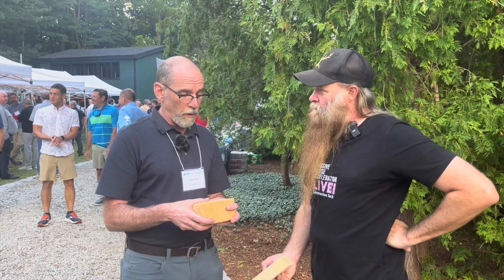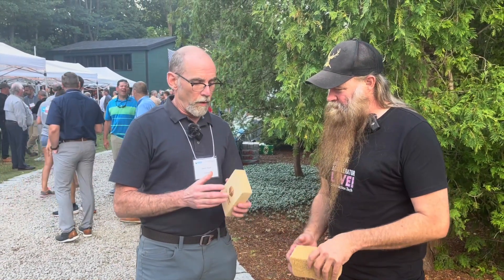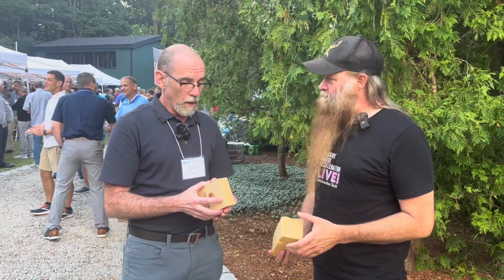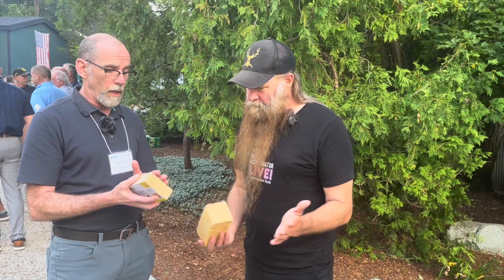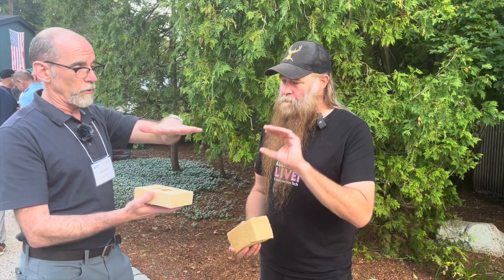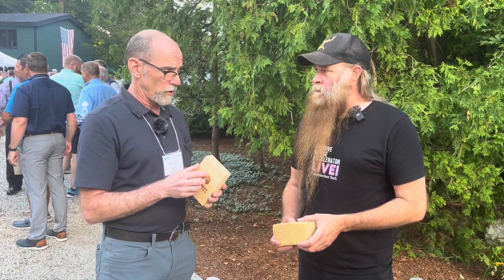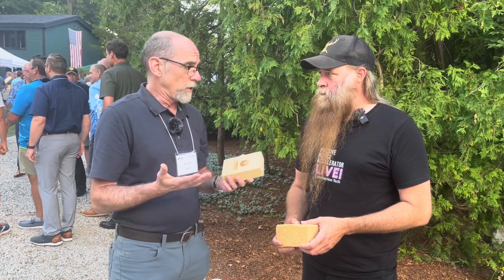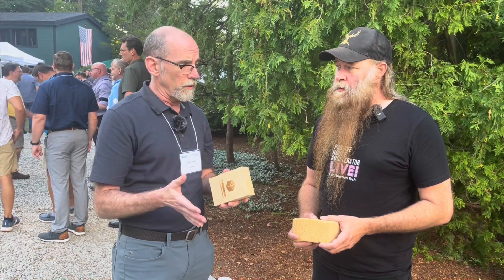There are some other properties about wood, especially when we get into the denser materials — the lack of compression that you get. You get reasonable R-value; it's similar to mineral fiber. We'll land at a price point somewhere between an XPS board and a Rockwool board. There's a huge carbon story when you talk about embodied carbon and the ability to sequester. We're taking a large mat and bringing that down in a continuous press until we get to the thicknesses we need. This board gives us about R5 per inch — an inch, inch and a half or so — which meets code for continuous insulation in climate zones four, five, and six.